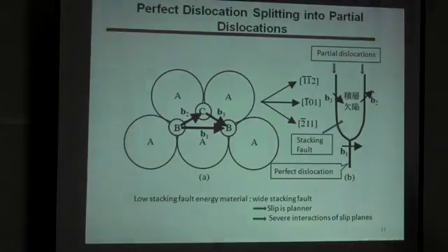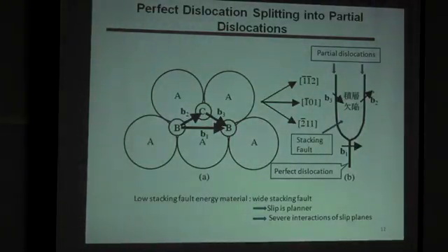And what's the mechanism of such kind of slip system? I will talk about it in the next slide. Okay, this is a typical dislocation you learned in undergrad school. This is a perfect dislocation whose Burgers vector is b1. But low stacking fault energy materials easily split into two partial dislocations, making a stacking fault in between the two partial dislocations. And this kind of low stacking fault energy material is very difficult to make cross-slip, because for the partial dislocations to cross-slip, they have to shift back to a perfect dislocation. So that's why low stacking fault energy material gives a very straight slip.